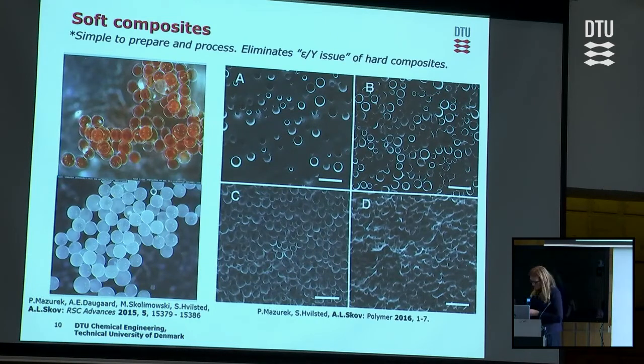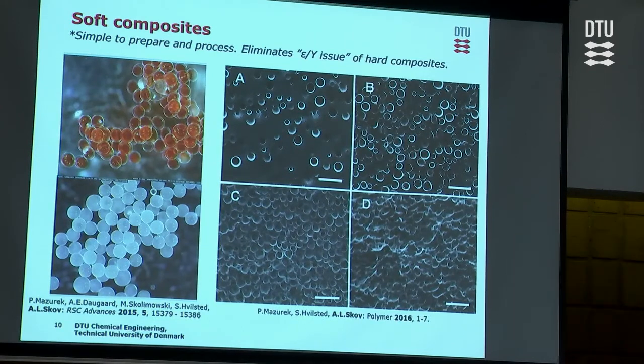And then after a year of hard work, Piotr Mazurek figured out he could actually just mix in the glycerol, speed mix it, and then we got very similar materials, but from a more or less one-pot experiment. And we could simply increase the loading of our glycerol, and then we would just have more droplets with approximately the same size. So that was a way to get an increased dielectric permittivity without getting an increased Young's modulus.